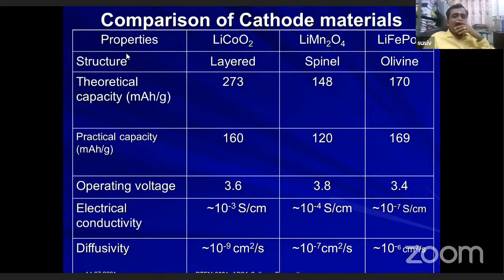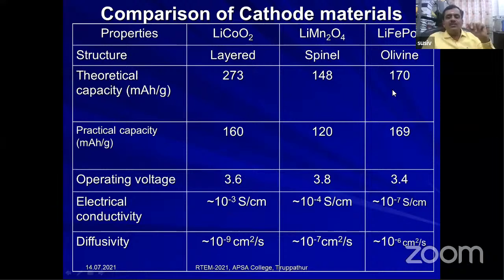Okay, sir. It is completely based on the structure. It has a layered structure. LiMn2O4 comes under the spinel structure, and LFP comes under the olivine structure. The theoretical capacities are normally 273, 148, and 170 milliampere hour per gram. How much can we attain from each material? For two-dimensional, we can attain only 160 out of 273, and 120 out of 148, whereas we can practically attain almost the theoretical capacity of LiFePO4, at a 3.4 volt operating voltage.